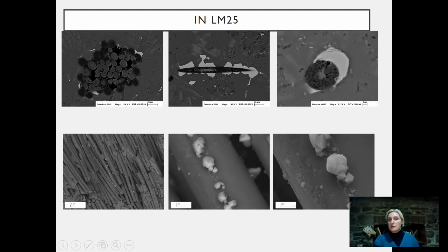This is extremely interesting. So what are these phases? Well, these phases are actually iron silicide. But we said they were needle-like. Yes, that's the beta phase. Also, we can have a polyhedral phase, which is an alpha phase. This is not detrimental. It doesn't have the same effect that the beta phase does. So this is a fantastic beneficial phase here. So we're trapping the iron around the fibers, forming beneficial phases.